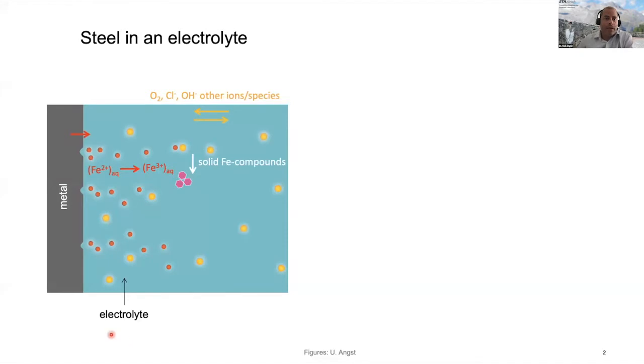If steel corrodes in an electrolyte, you are very well aware of the different processes that occur, such as the dissolution of iron from the metal into the electrolyte, where ferrous ions are formed. These ferrous ions may then be transported away by different mechanisms, including diffusion, migration, or advection, and they may also be oxidized to the ferric state. And in the electrolyte, these ferrous and ferric ions may also meet other species shown in yellow here, such as dissolved oxygen, chloride, or hydroxyl ions. When they meet, they may form complexes or compounds, including some sparingly soluble compounds that may then precipitate.